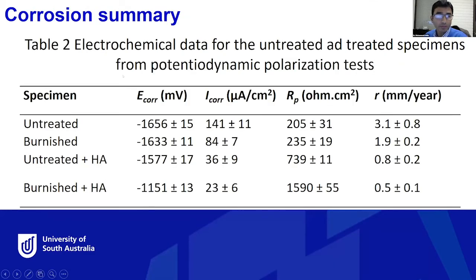And this is the summary of the corrosion results we have got here. This again indicates that the burnish plus HA coating is giving the highest corrosion resistance compared to the untreated or even the simply burnished surface. As you can see, the corrosion potential is higher, and the corrosion current is also lower. So that means higher corrosion resistance, in fact.